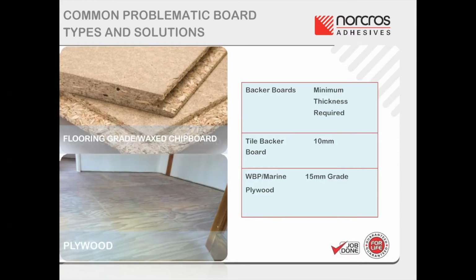Two common types of problematic timber floors include plywood and chipboard. When tiling to plywood floors, always ensure that the plywood is a high-quality Class 3 external grade WBP or marine grade plywood as recommended in BS 5385 Part 3. There has been an influx of cheap low-grade plywood which is often impregnated with an oil which inhibits adhesion and prevents the adhesive from bonding, resulting in delamination at the plywood to adhesive interface.